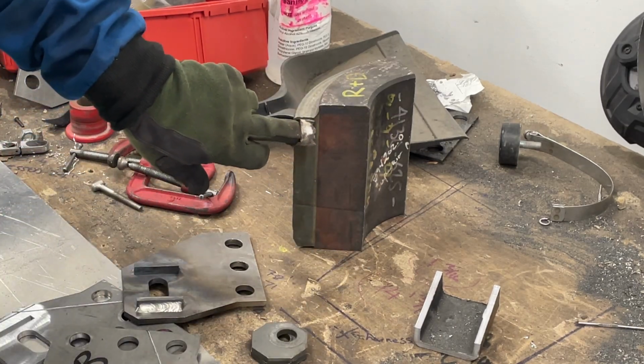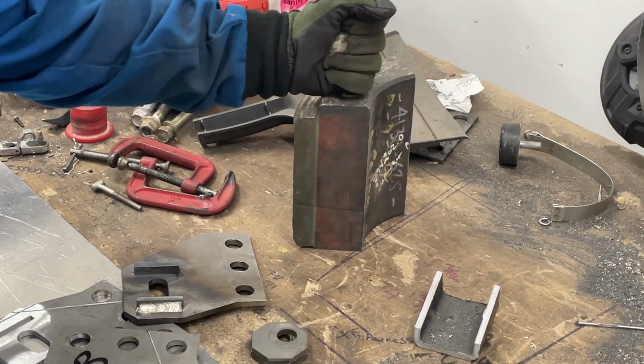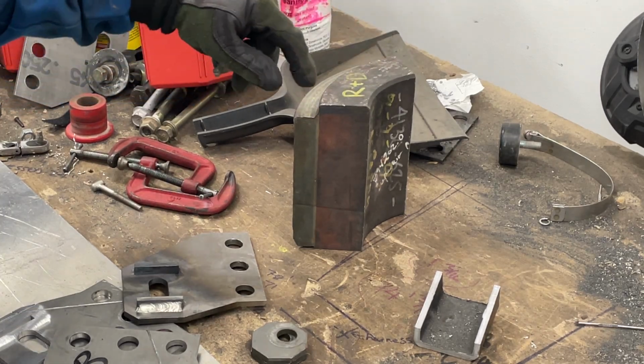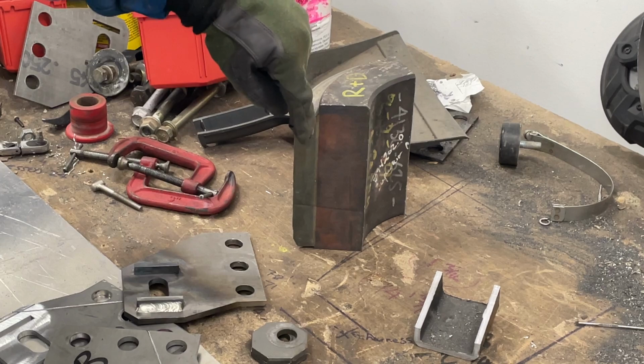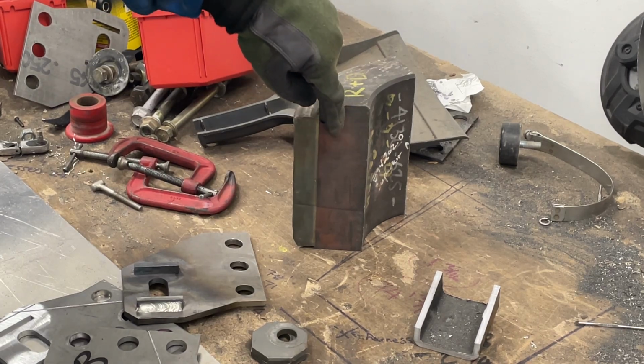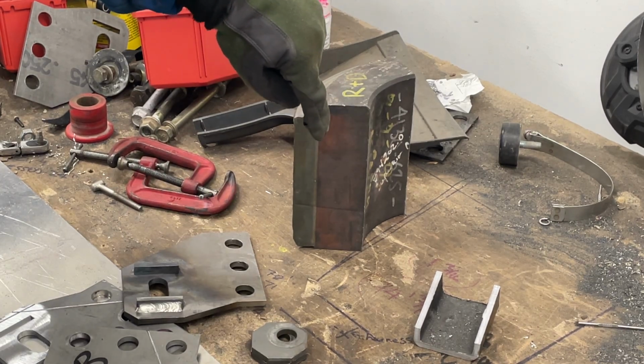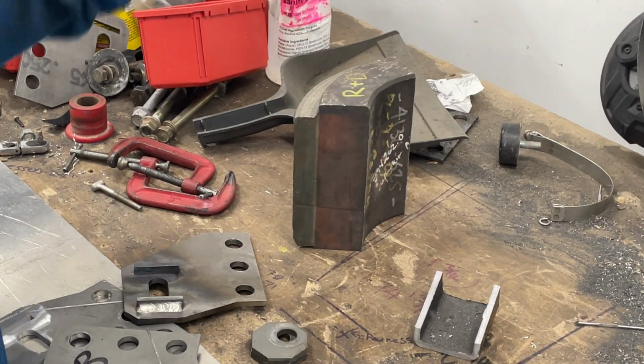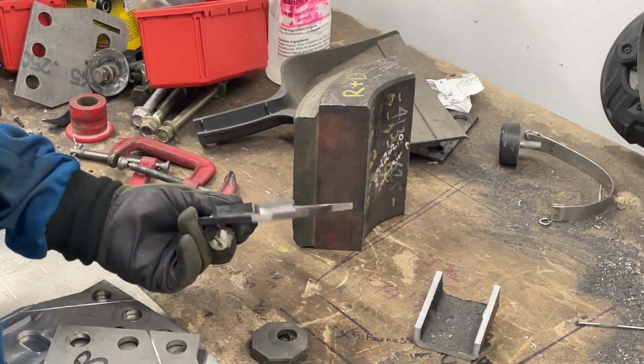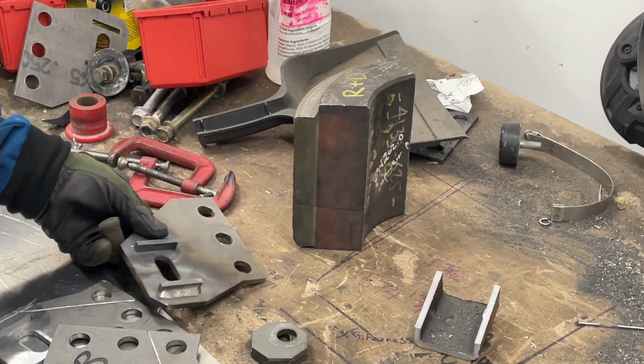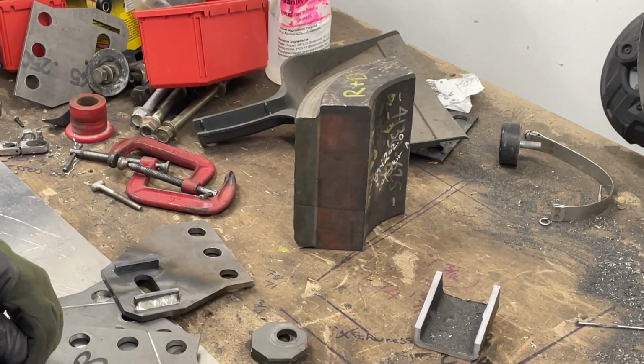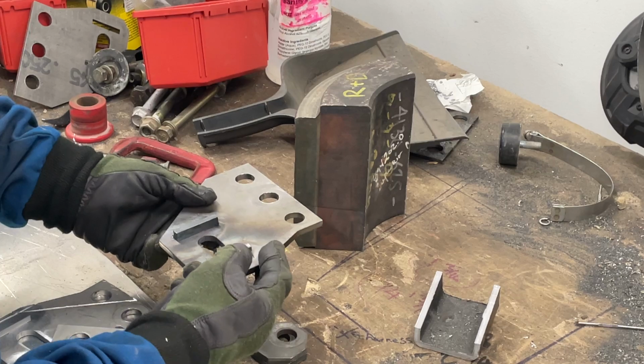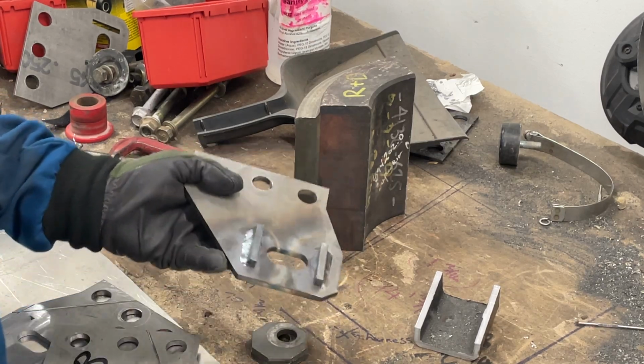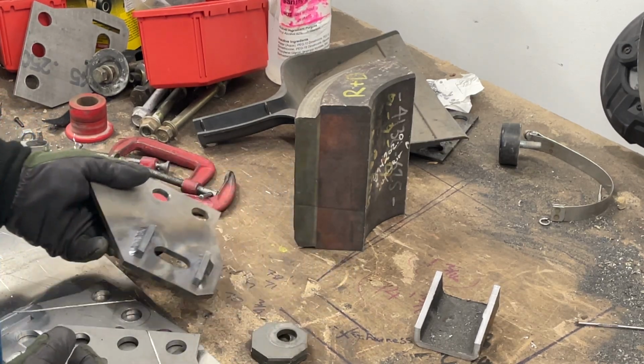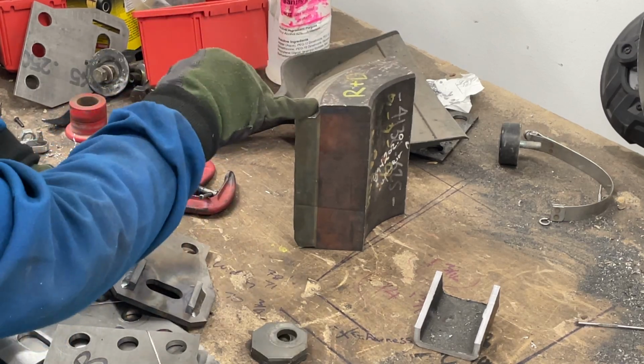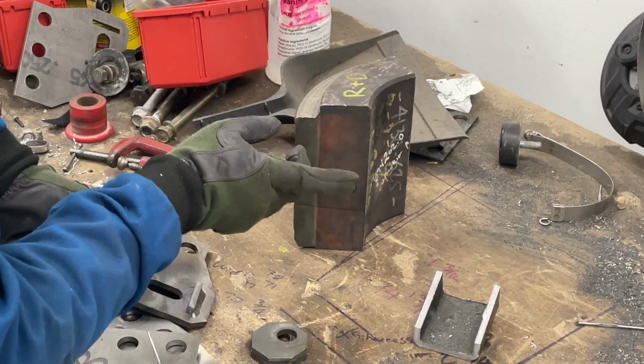A formal post-weld heat treat actually has a real deal hardness criteria, as in this weld cannot be harder than this, the base metal can't be harder than that, and the heat affected zone cannot be harder than the other criteria that would be listed. So a stress relief, you don't have that kind of stringent criteria. With a post-weld heat treat, you do. So when you hear people talk about stress relieving, it's usually a more secretive, a shop figured it out type of criteria, where a post-weld heat treat is a formalized standard practice that people follow for welding.